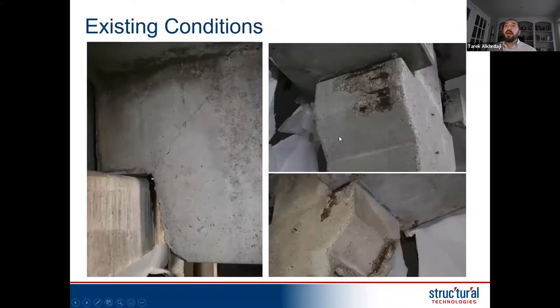This is a parking garage. The parking garage was going into significant corrosion, mainly because of the deicing salts they kept using on the top side, coming in, infiltrating into the elements, and restrained for movement, like I mentioned to you. The combination of the two caused some of these corbels actually to corrode to a level that there was a collapse in the parking garage.